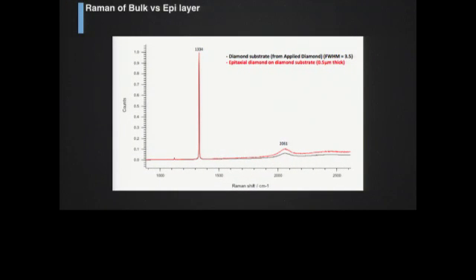So the first thing that we did is we tried to calibrate the quality of our system. We took some high quality bulk grown diamond, and we grew epitaxial films on it. One of the easiest, straightforward experiments that you can do is measure the full width at half max of this peak, which is indicative of the quality of the diamond. Pure diamond has just this one Raman peak here, and the full width at half max tells you about the quality of the crystal structure.